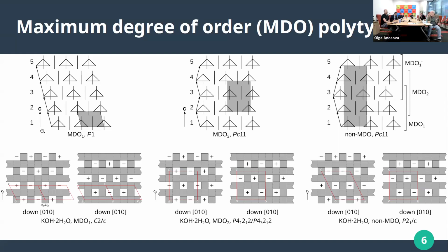Because simply, if you take one of the central layers and that has a reflection plane here, and you take the 2 other layers that violate this reflection plane, then you will have some distortion inside this layer, and the reflection plane will not be perfectly realized. So what will happen is that triples will be slightly energetically different. So one may be better than the other, lower energy.